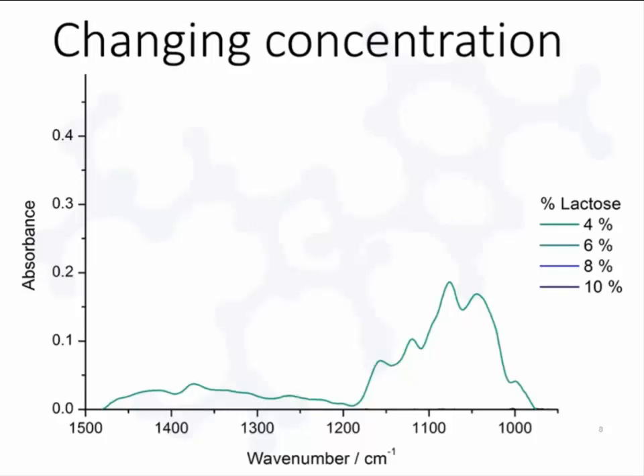So here's an example of spectroscopy where there's a direct application. The quantity of lactose in dairy milk varies depending on a cow's health and how far she is in a pregnancy. So the dairy industry like to monitor the lactose levels in their milk samples. Here is the absorption spectrum of a solution of 4% lactose. And you can see that there is an absorption occurring centered around 1400 wavenumbers, and a much stronger absorption centered around 1050 wavenumbers. And that's the signature that we'd get from the lactose at a 4% solution.